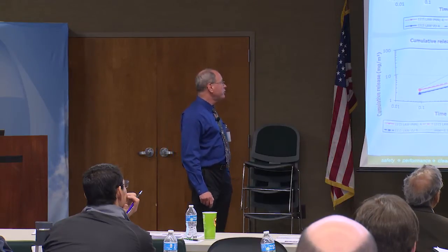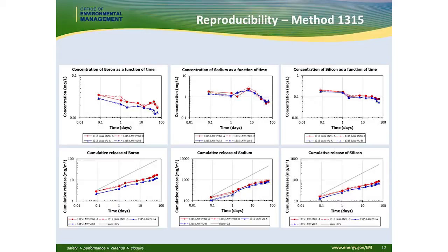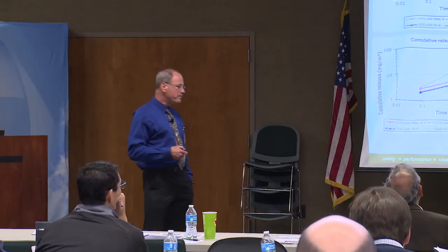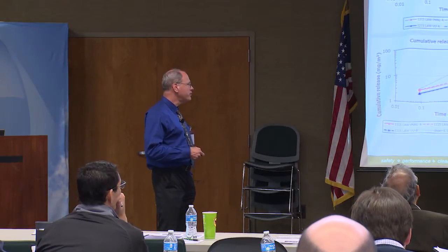And then we looked at method 1315, and you'll see two different plot representations here. This is concentration as measured from the test, and again, very reproducible. And then cumulative release, which is looked at over time, in milligrams per square meter. And again, fairly reproducible. This is from before, while we were still working out the sample prep, so I expect that the reproducibility of the final results will be better than what we see in this preliminary screening.